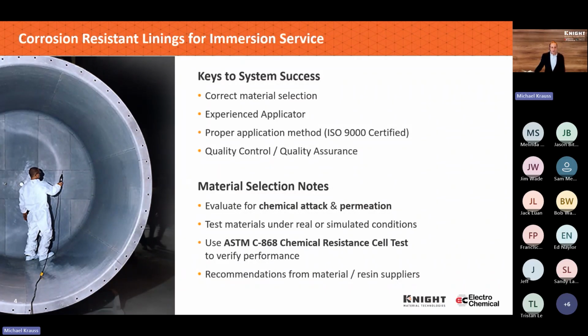There are corrosion guides that are out there that look at chemical attack, but they typically neglect permeation. The preference is using the corrosion guides or material and resin suppliers as a really good starting point. But if you have the capability to do either Atlas cell testing according to the ASTM standards, or even put a line blind flange or manway cover into service, it will give you a huge opportunity to get real world data. And it's also tricky looking at the corrosion guides.